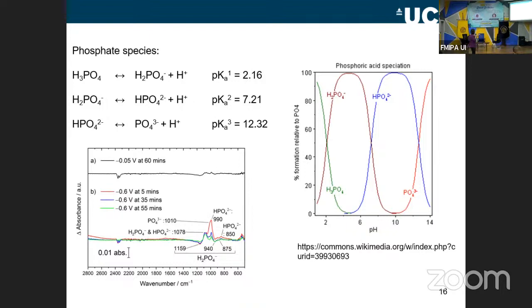So this diagram here is just a different way of showing these. It's telling us which acid species are present in the solution at different pHs. So here I have pH, and this is the relative amounts of the different species. So in the acidic solution, I start with lots of H3PO4, but as I go to less acidic solutions, this goes down and the H2PO4- goes up. And then this starts to go down and the HPO4 2- goes up. And then finally, under the most alkaline conditions, I get an increase in PO4 3- and a decrease in the HPO4 2-.